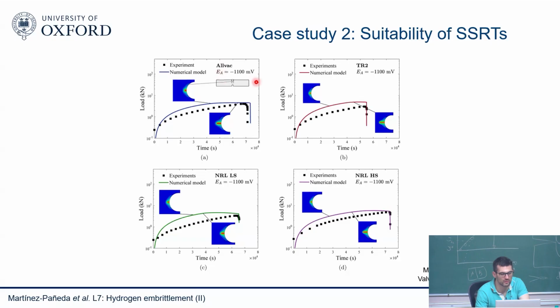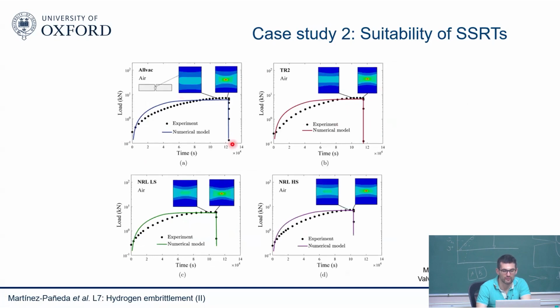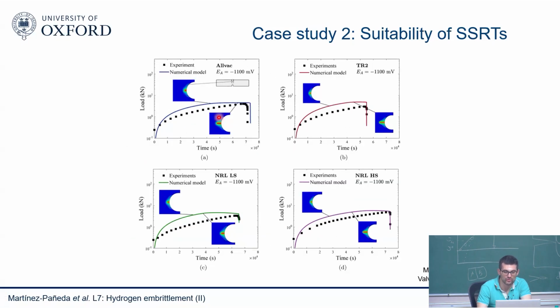This is for a given applied potential. It's quite an aggressive one, so it introduces a lot of hydrogen, and you can see how the crack initiates. There are 2 interesting phenomena here. First of all, the model can naturally capture the transition from ductile fracture, with failure starting in the center as seen in the experiment, to failure at the edges happening much earlier due to the embrittlement. So the model captures the embrittlement well. The other key observation is that we don't tell the model anything about when cracks need to start or grow. The model predicts some initiation of crack growth relatively early in the test. How early depends on the material. Then we see crack propagation, and eventually crack failure in good agreement with experiments.